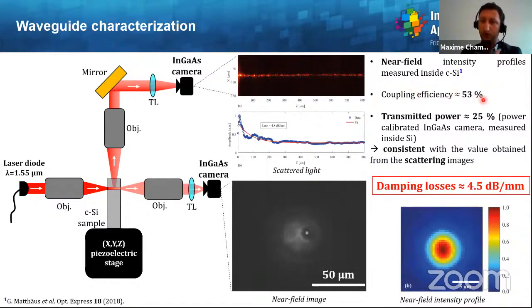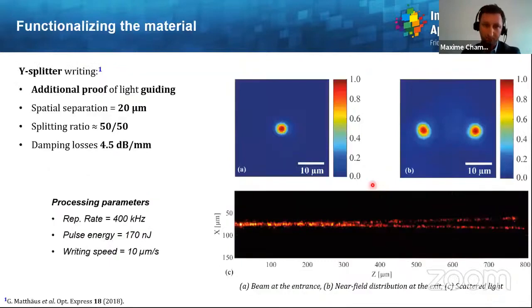So what we concluded on those measurements is that we had some coupling efficiency of around 53%, a transmitted power of around 25%, which is consistent with the value we obtained from the scattering images. And moreover, the damping losses are between 4 and 5 dB per millimeter, which is much lower than what we had before with the nanosecond pulses.